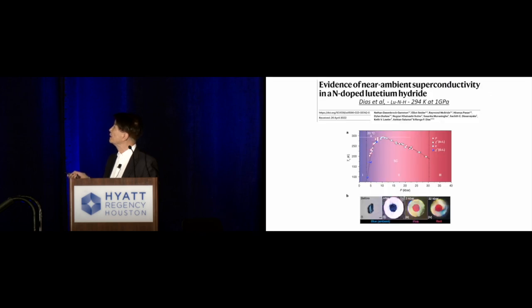And then there was the work by Dias I mentioned. They claimed they found 300 degrees Kelvin superconductivity with only 10 kilobars, that's 1 gigapascal. In fact, when they announced these results, they immediately set up a company. They got tens of millions of dollars from venture capital, including Bill Gates and those people. I don't know what they do now, when this is not true and cannot be reproduced.